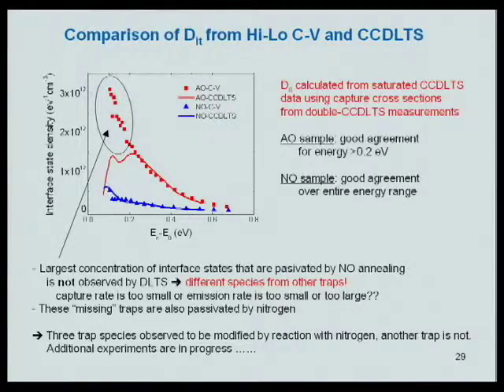So that's telling us that the traps are some different species still from the ones that we detect because we don't see them. And so not only are two of the trap species that we see changed by nitrogen, but also the ones we don't see are changed as well. And then what we find is that we get very good agreement between the standard method and our method of calculating this for the nitrided samples. And there's basically the dominant trap in these is one species that is also present here that's not affected by the nitrogen annealing. Okay.